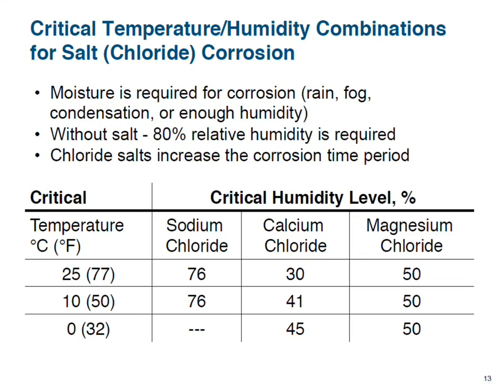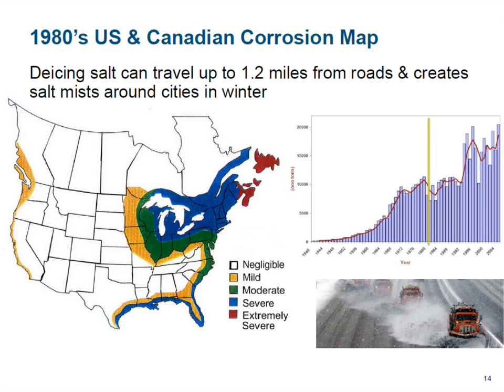Calcium chloride and unfortunately sometimes magnesium chloride are increasingly being used for de-icing. When those are present in the environment, then you only need 45 or 50% humidity, and as soon as you're above freezing, they are actively corrosive. In the case of the arch, the highways are some distance away. But if you're working on a project where there are roads immediately surrounding it, finding out what a city or municipality is using is quite important.